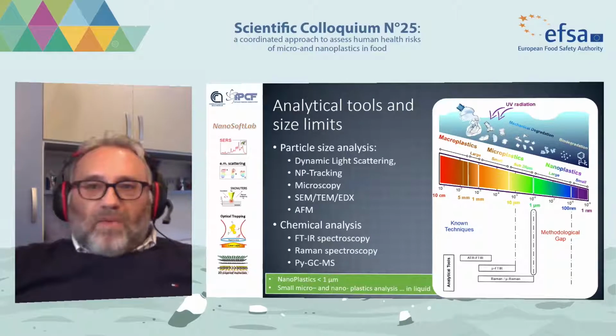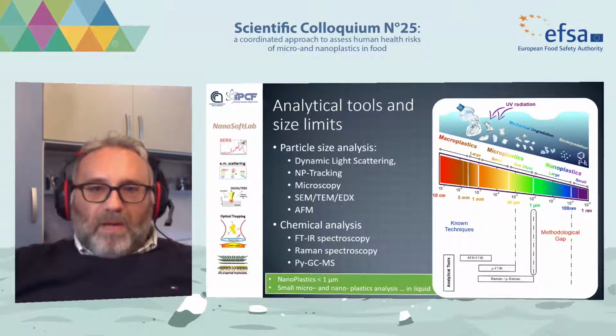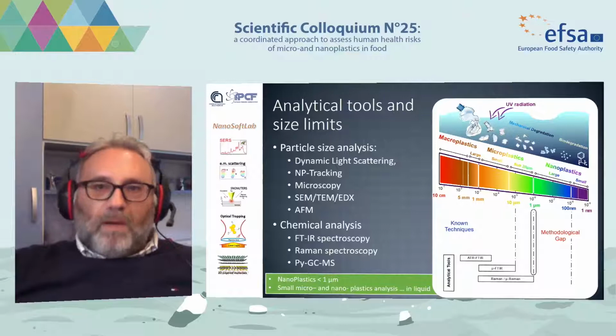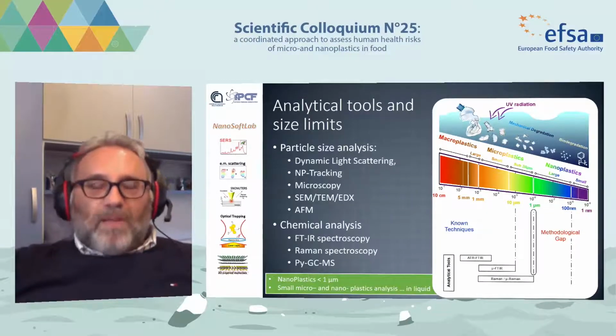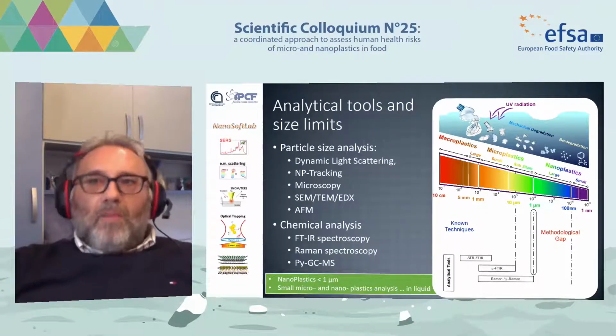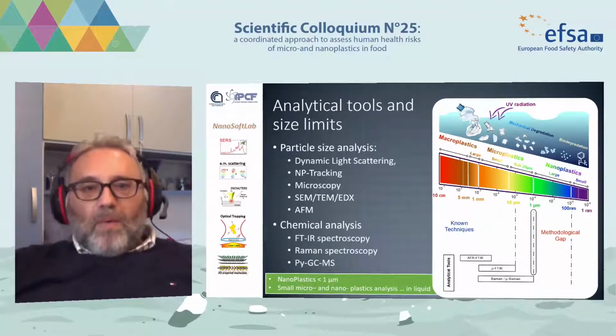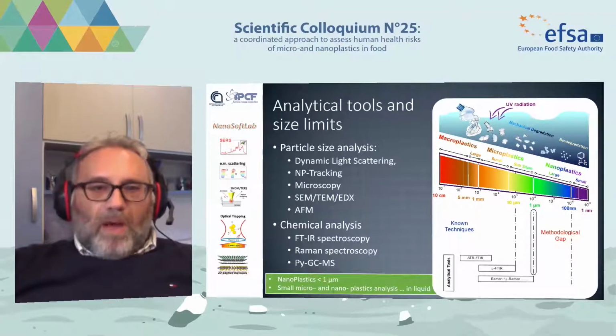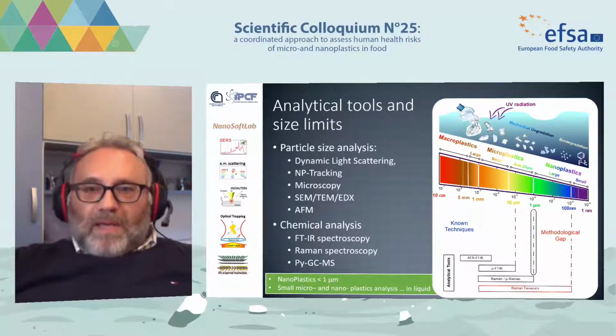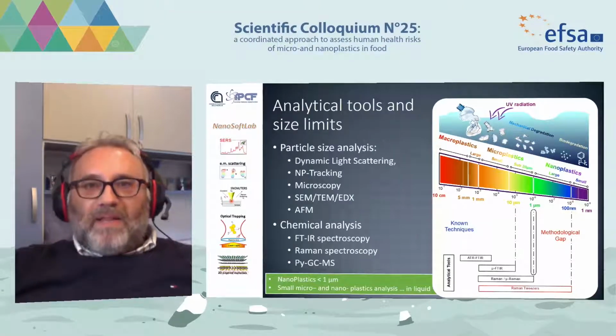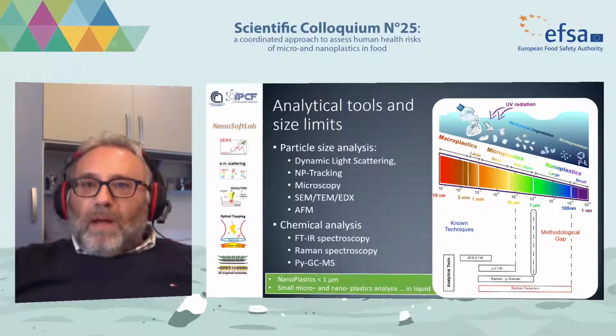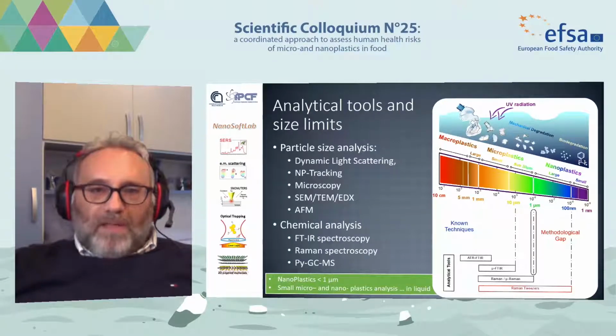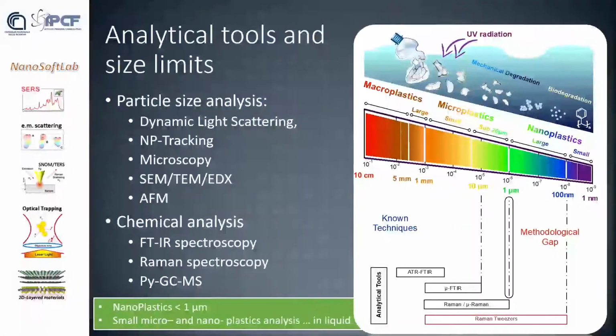And then the question is, of course, separating one or more particles, because there is the so-called diffraction limit in optical microscopy that prevents us from separating particles that are closer than, I would say, 250 nanometers. Okay, we can detect, but we cannot say if there is 1 or 2 or 3. So another problem is that we have a serious methodological gap if you want to measure particles directly in liquid. In the examples shown up to now, if we dry the particles, then we can analyze them, but when we go in liquid, we have serious problems to do this.